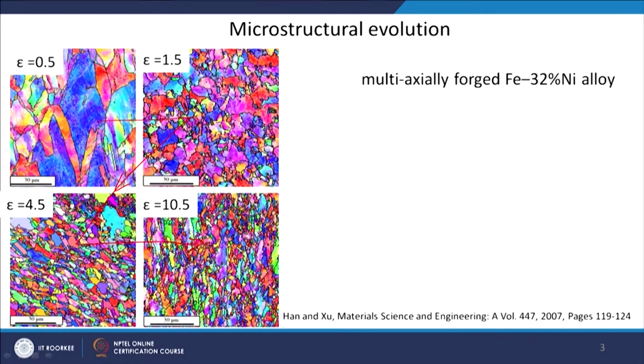Then by the next cycle, at a strain of 1.5, you can see that the grain is now getting fragmented into smaller grains. Some fine grains are there, and still some coarse grains with some substructure. If you try to see the strain from here to here, you will see some strain gradient in the grain. Now you start seeing even more fragmentation of the grain. Some very fine grain structures are there, and still some coarse grains are there, for example this and this one. And of course, you have even more refinement after a strain of 10.5. Though the structure looks heterogeneous, there are coarse grains as well as fine grains. This is the work done in an Fe-32% nickel alloy, multi-axially forged.